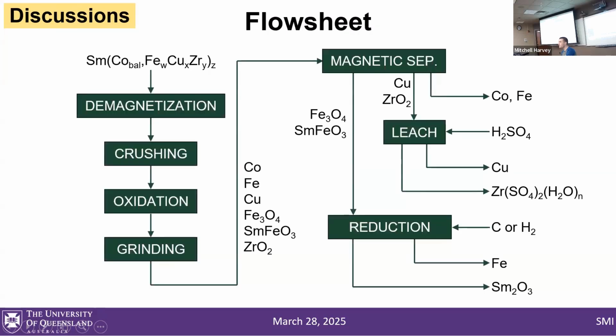This is the process—the flow sheet—that we've developed. First we take our scrap magnets, crush them to increase the surface area, perform our selective oxidation process, then grind them to liberate the phases, leaving us with a mixture of cobalt metal, iron metal, copper metal, magnetite, samarium ferrite, and zirconium oxide. We then do our magnetic separation.